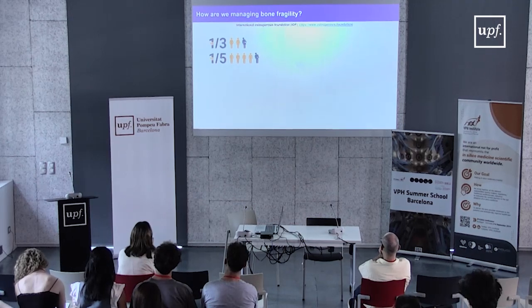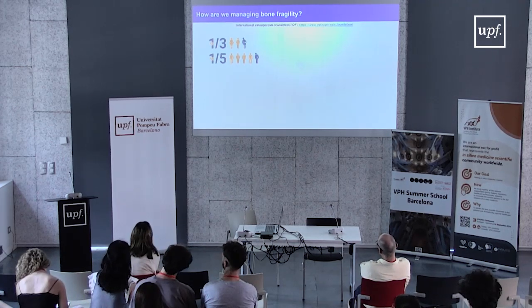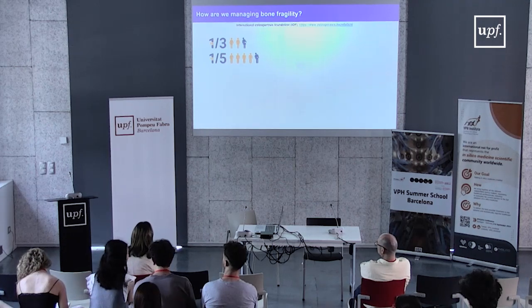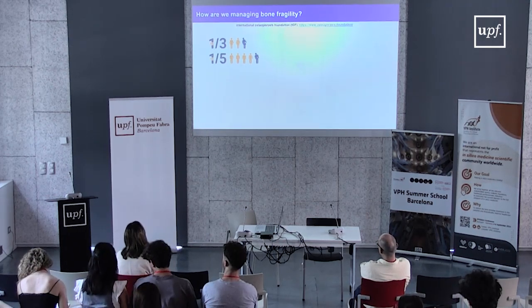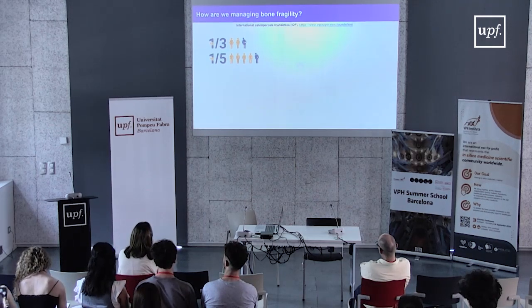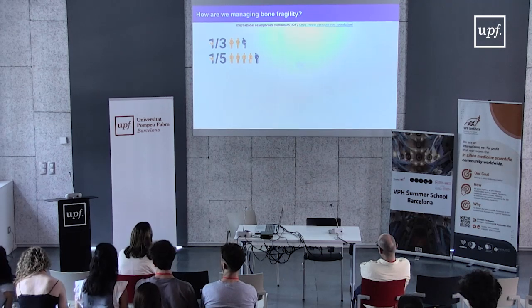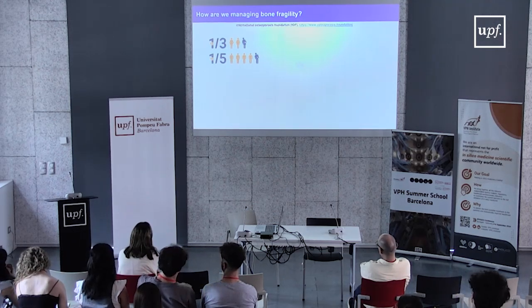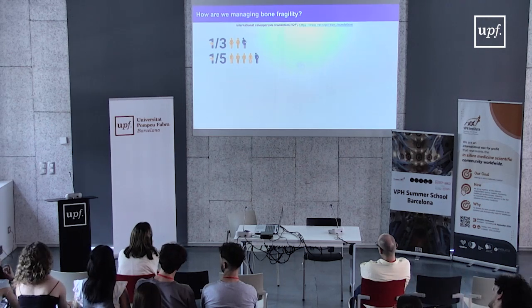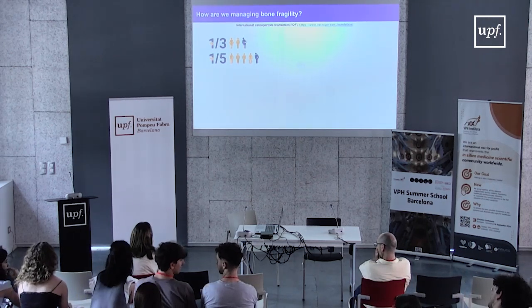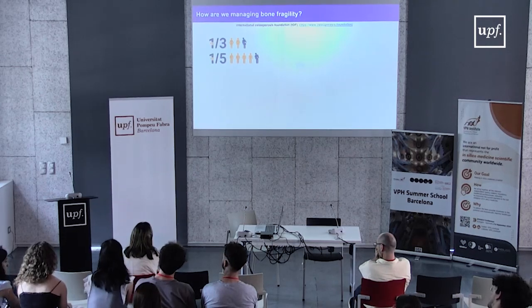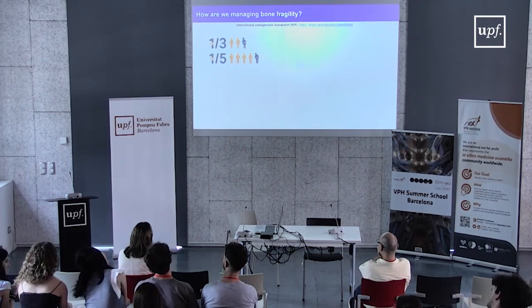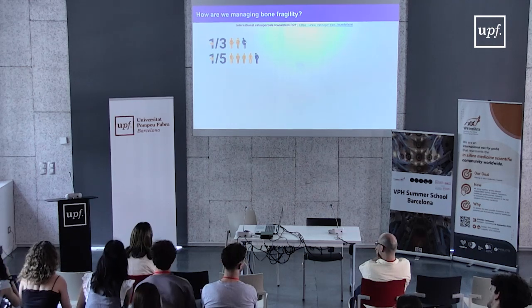So if we move a bit from the cell biology to the clinic, and how we actually manage bone fragility and how drugs which are used to manage bone fragility are effective at the different scales: osteoporosis, which is a major bone fragility disorder, is quite common, especially in our aging population. It will affect 1 out of 3 women after the age of 50 and 1 out of 5 men after the age of 50. And it's not only that you suffer from a low bone mass, which is often described as osteoporosis, it's that 1 out of 3 women and 1 out of 5 men will develop a fragility fracture after 50 years old. So you see it's quite common.